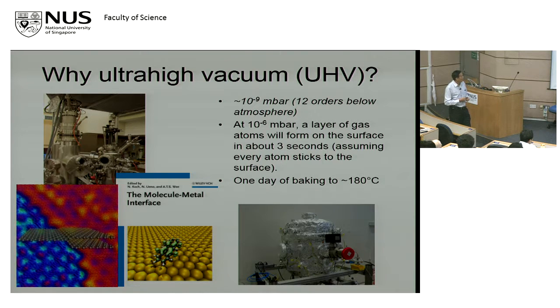So why do we bake it? Typically we either cover it in foil or put it in a big case oven and then heat it to 180 degrees or higher for at least 1 day. By heating the stainless steel and everything to that temperature, you accelerate the degassing process. Because where are all the molecules? They are all sticking on the walls, right?